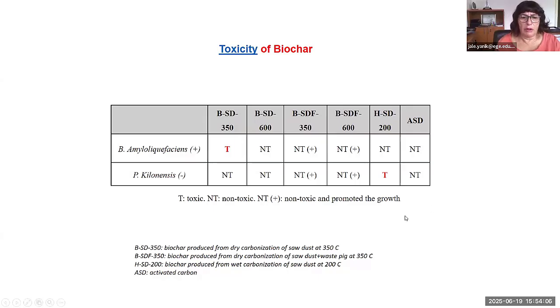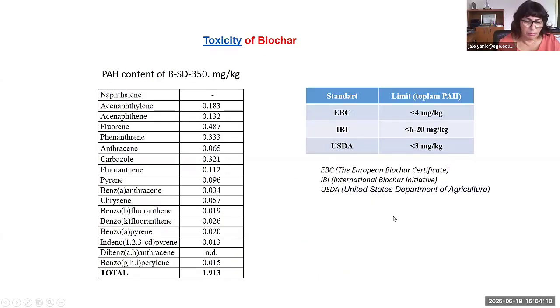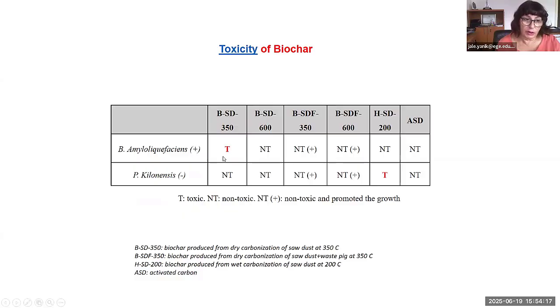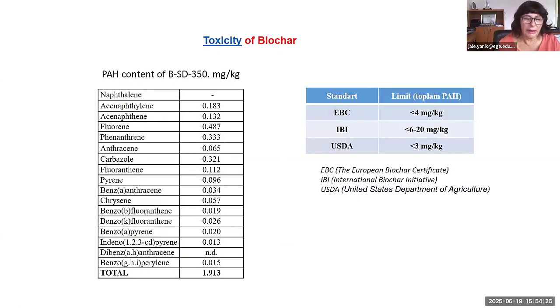At first, we thought that this biochar from sawdust is toxic for gram-positive bacteria. We thought maybe the PAH content was high, so we determined the total PAH content of the biochar. As you see, the total amount was lower than the limit. Of course, these PAH limits are for soil, but we don't have any standard PAH limit for microorganisms.